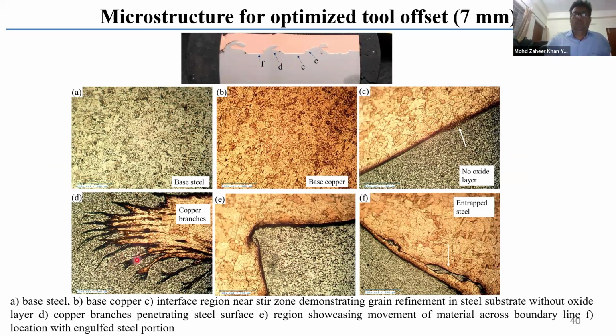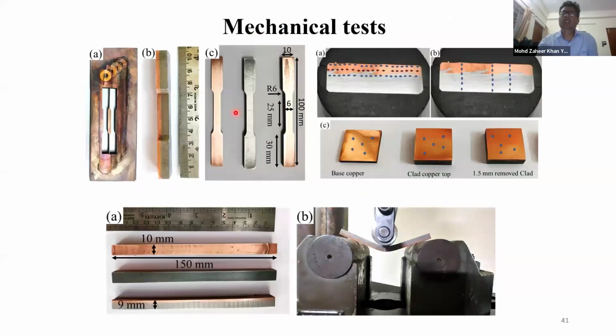out, bend test was carried out, and this is the result of the bend test. After the plate has been cut and it was bent in a tensile testing machine, you can see even after bending in all the three directions, no disbonding is actually taking place.